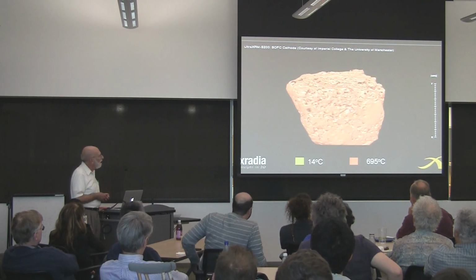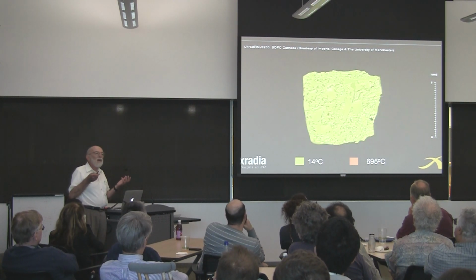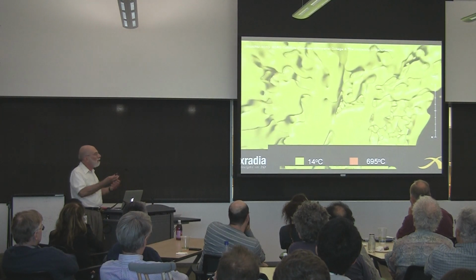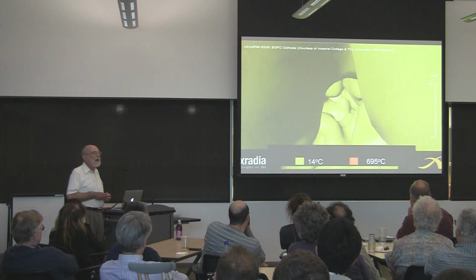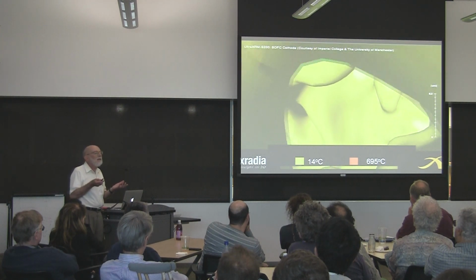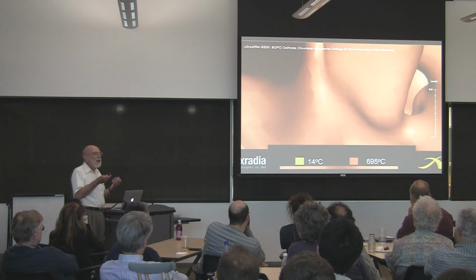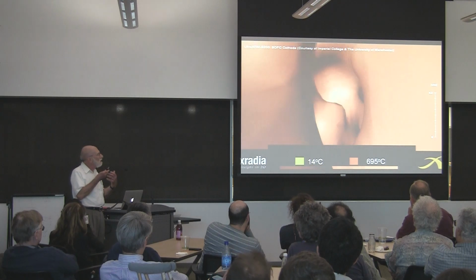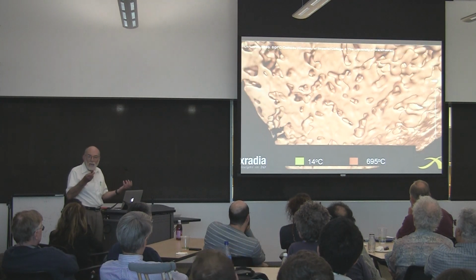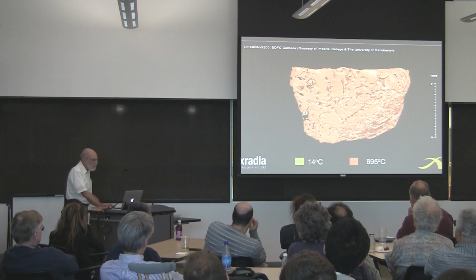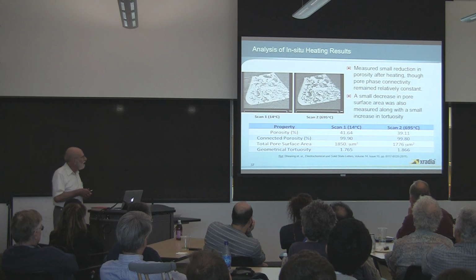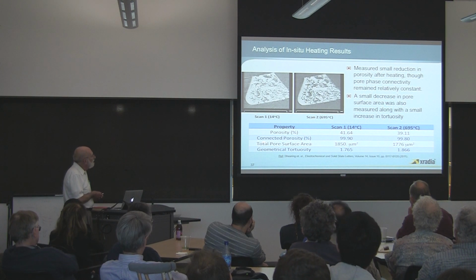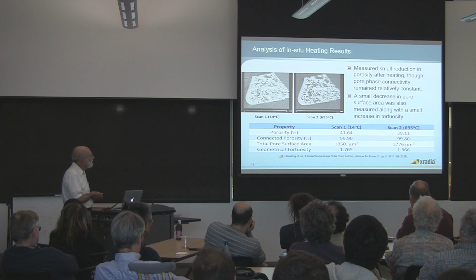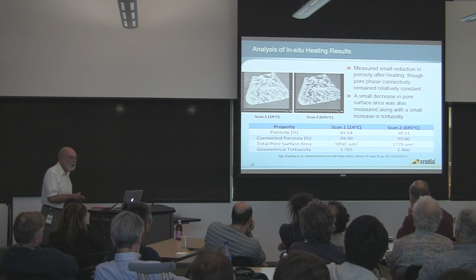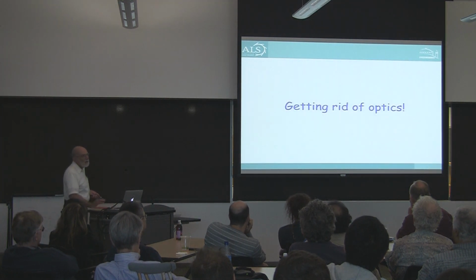This is a small piece. The scale bar is here. It is 7 microns across, and you will see that we are going to enlarge it in a moment. The thing is, you want to understand how the gases go through the structure of the fuel cell, but the fuel cell operates at roughly 800 degrees. And so one of the questions is, how does the structure of this fuel cell change as you go from room temperature to the operating temperature? So X-ray microscopy is capable of quantifying the porosity as a function of temperature, the connectiveness of the porosity as a function of temperature, the total pore surface area, and so on. And so this is where much of the growth has come from.